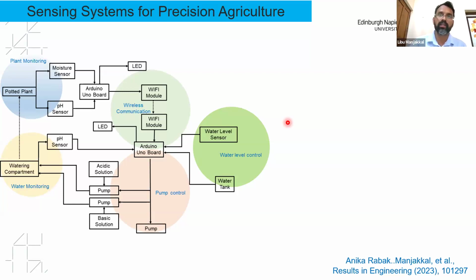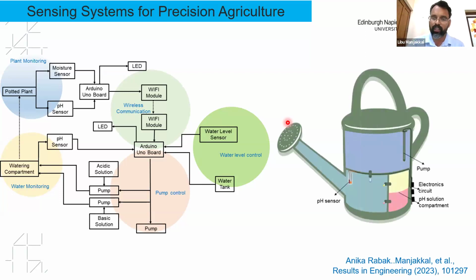So how can we simultaneously monitor the water being poured, especially in a home garden, the water you drop on top of the soil, and at the same time monitor the soil pH? What we did is make an automatic system where we developed a pH sensor built into the soil, where we dipped it in the soil, and the sensor is also integrated on a smart watering can. So if your soil pH is, for example, 5.5 and you need a pH of 6, you can pour water with a pH of 6, adjusting the pH value of the solution, and you can monitor the pH value of the water you are pouring.